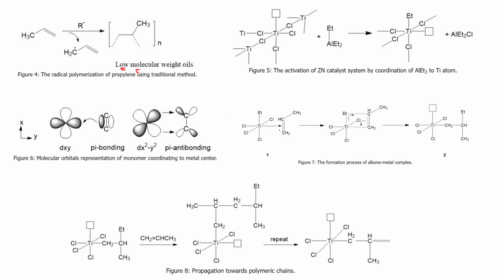When it reacts, you can expect formation of a four-member transition state followed by this kind of shift. That would lead to titanium-carbon bond formation, and this particular bond would be flipped. So this ethyl group is now attached to that polymer chain, or alkyl chain, you can say.